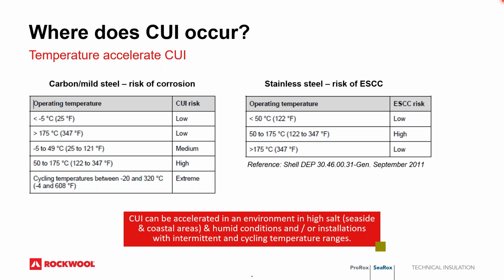CUI has a range where there's high risk. The slide in front of you demonstrates the various ranges of temperature of your process where CUI risk is low to extreme. And of course, you notice quickly that the extreme temperature is on a cycling system that cycles between, say, -20 Celsius up to 320 degrees Celsius, also known as -4 to 608 Fahrenheit. But the high risk zone that is more common in many of our facilities is from 122 to 347 F. And of course, accelerated risk areas are any facilities near coastal areas, because salt water helps accelerate the corrosion, or high humidity areas. And as mentioned, if you happen to have a cycling facility, that puts us into a new extreme as far as what we need to concern ourselves with regarding corrosion under insulation.